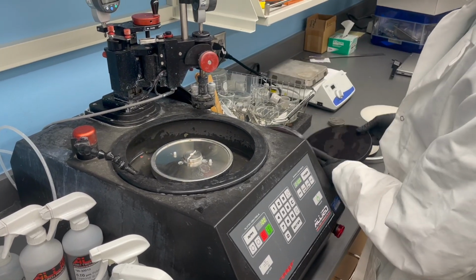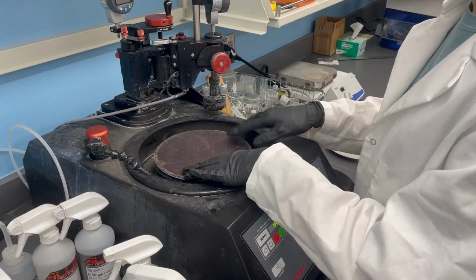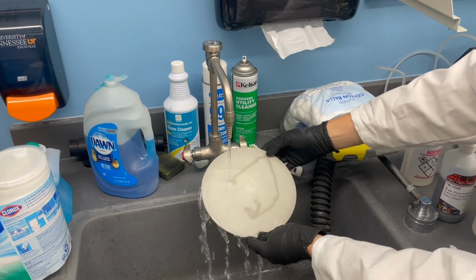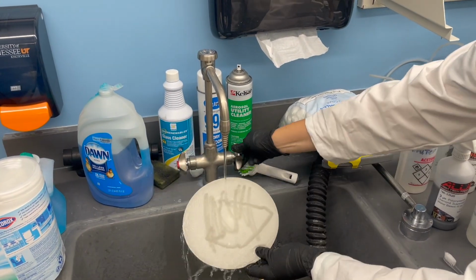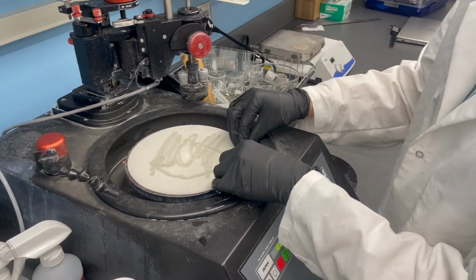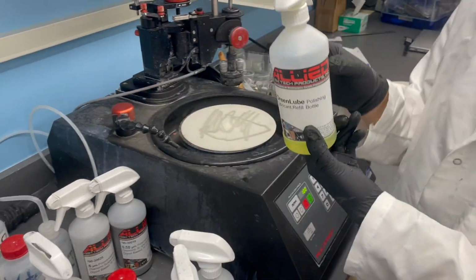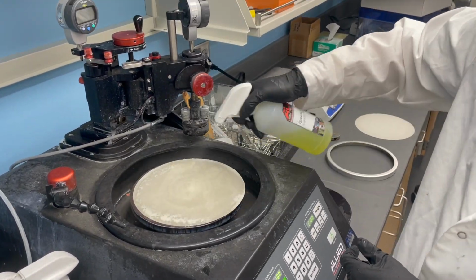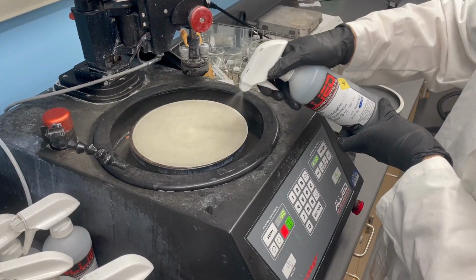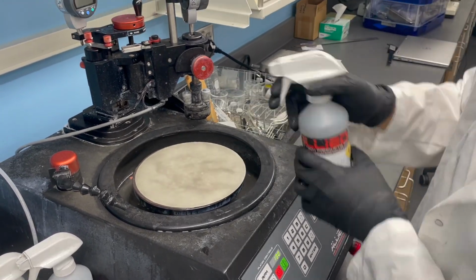After all the grit papers have been used, replace the platen for the magnetic one. Start with a 3-micron polishing pad. Lightly wet the pad before placing it on the platen. Spray the polishing pad with a green lubricant and the 3-micron diamond sprays. Reapply sprays every 3 to 5 minutes until sample surface is pristine.